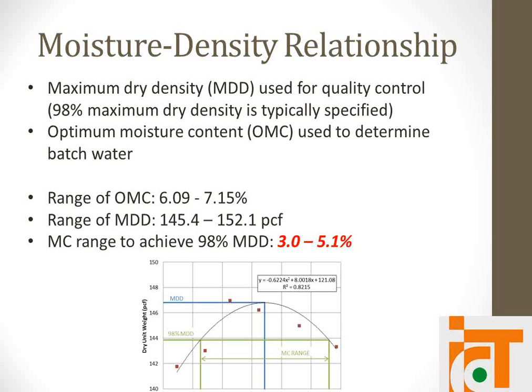So then designing the mixes, you do a modified Proctor test. Anywhere from 5 points gave relatively good curves, and some had to use 7 points to get a good fit. And from that, you use the maximum dry density for quality control in the field. That's how they would specify the minimum density. And your optimum moisture content is what you aim to batch the concrete at. And we've seen that it's quite susceptible to the optimum moisture content. If you're too wet, the mix will segregate under the roller and won't support it. And if you're too dry, you won't be able to achieve density.